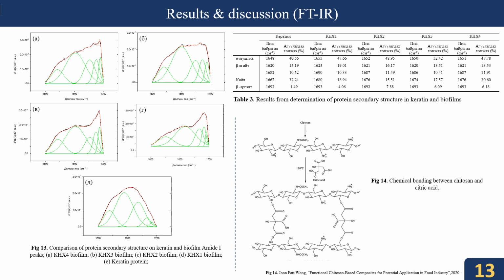Also, as shown in the figure on the right, the absorption of amide 1 and 2 of biofilm mixed with chitosan and citric acid becomes sharper and increases, which is similar to the results of our research. So in the mixed biofilm of keratin and citric acid, the absorption of the hydroxyl bond of the citric acid decreases and the proportion of the protein alpha helix increases, which is similar to the result of other biomaterials produced using citric acid. Therefore, successful connections between keratin and citric acid indicate the formation of the biofilm due to the addition of citric acid between the carboxyl groups in the keratin polypeptide chains.